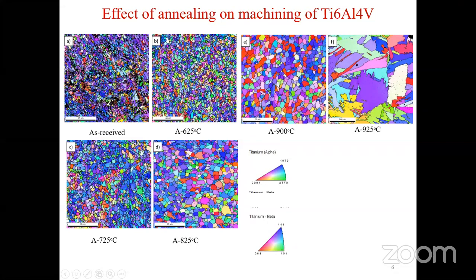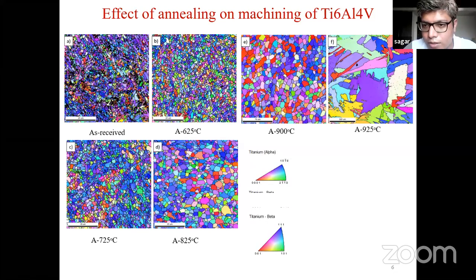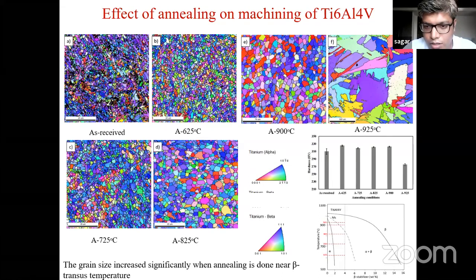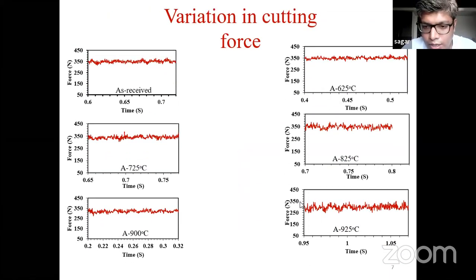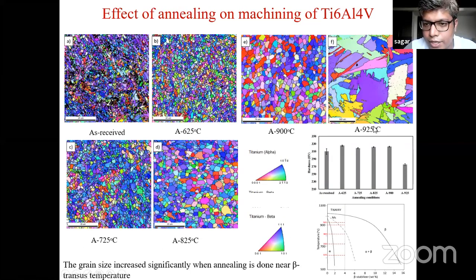Okay, sir. So what happened here is, let me put it another way. Here, the depth of cut was almost near the grain size of the sample. So when the depth of cut is of a length matching the grain size, and you cut this grain, then another grain of similar size comes into the picture. So there will be local orientation differences occurring while machining. That's how the grain size is affecting the machining.